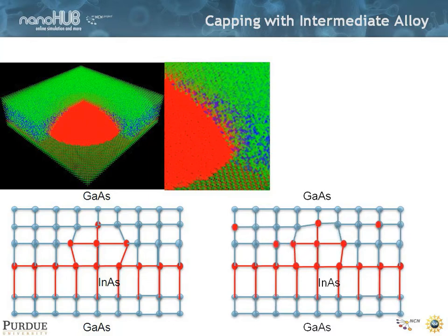So you throw in more indium around it that gives the center quantum dots less chance to push laterally. So the only way they can push is vertically. That means you increase the biaxial strain in the system.